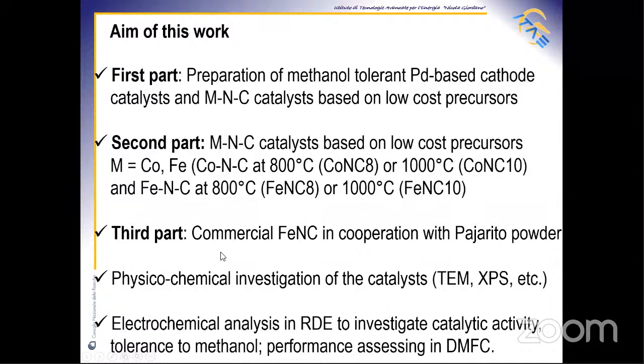In the third part, we talk about the results obtained with the commercial FeNC in cooperation with the Pajarito Powder. All the catalysts were physicochemically investigated with TEM, XPS, XRD, and electrochemically analyzed in rotating disk electrode to investigate the catalytic activity and the tolerance to methanol, and the performance was assessed in direct methanol fuel cell.